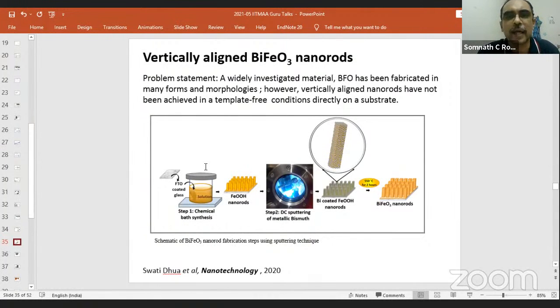So bismuth ferrite, as you can read here, the chemical formula, BiFeO3. This is a very special compound. This has got ferroelectric property, ferromagnetic property, and then photovoltaic property, meaning it has very good ferroelectric and piezoelectric property in one, and then ferromagnetic property, which is called multiferroic property. And also it has an optical band gap of around 2.4, 2.5 electron volt, which means that it can absorb up to about yellow-green light in the solar spectrum.